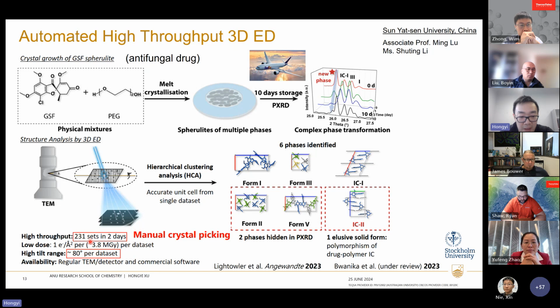So each data set is pretty much complete for structure solution if we want to. So over 2 days, we collected 230 sets of data. And then out of these 230 data sets, we actually identified 6 different phases. So 3 of them we could see from powder, 2 of them were hidden, and then 1 was a very, very minor phase. No, sorry, form 2 was a very minor phase. And then within the powder, we also see the original form that our collaborator has grown.